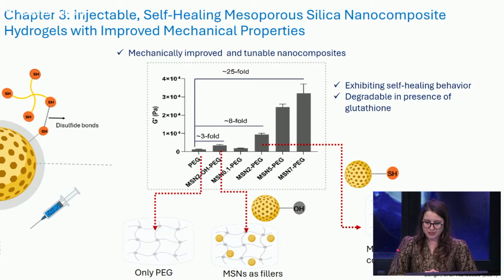And when we look at this rheology data, we can clearly see the impact. When MSNs are dynamic covalent cross-linkers, they can improve the mechanical properties significantly. But on the other hand, when they have these hydroxyl groups on their surface, they cannot interact with the PEG backbone, and they function as fillers, so their mechanical contribution is limited. And what is exciting is these improvements in the mechanical properties didn't disrupt the self-healing behavior of these hydrogels. They still show self-healing behavior, and also these hydrogels were redox responsive, so they were degradable in the presence of glutathione, which is a reducing agent found in the body.